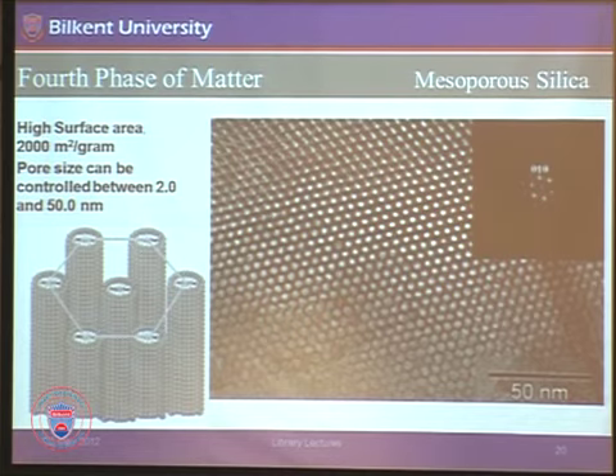If you put chemicals that polymerize and go into solid state, and put them in between those domains, you can get materials that you cannot make by any other means. What I mean is, for example, glass is a silica. If you put molecular glass, which dissolves in those media, they can go into these domains because these are the ones they like, and they start polymerizing in this region and getting rigidified. This material to start with is a soft material. When they go and polymerize in those regions, they become solid.